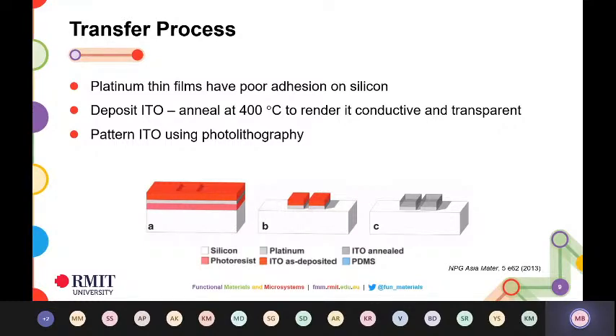So in this particular case, you have ITO, which is being deposited by electron beam evaporation. It's being annealed at 400 degrees centigrade and also patterned using photolithography. So what you see in that image C over there is platinum sitting on top of silicon. Now we spin coat and cure the conformal stretchable polymer, PDMS, on top of this.